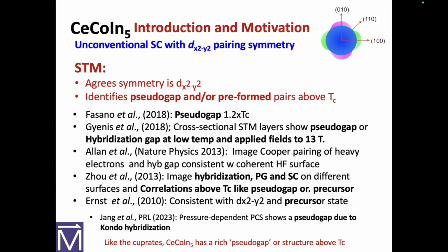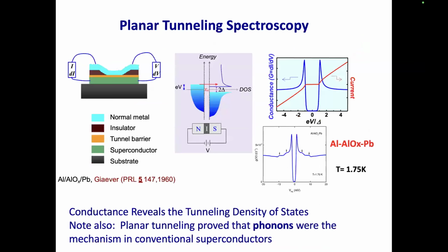A recent publication, PRL 2023, using pressure-dependent point contact spectroscopy with my old student in Tucson, Park, showed that indeed there is a pseudogap due to Kondo hybridization, which I think they're completely correct on. But I think the bottom line is, like the cuprates, CeCoIn5 has a rich pseudogap structure. So above Tc, you're certainly going to see the hybridization in the transport. But within that pseudogap area, our data are consistent with the possibility of preformed pairs.